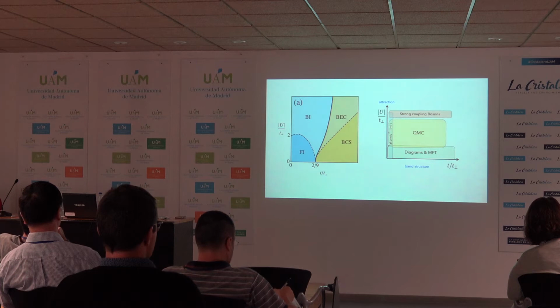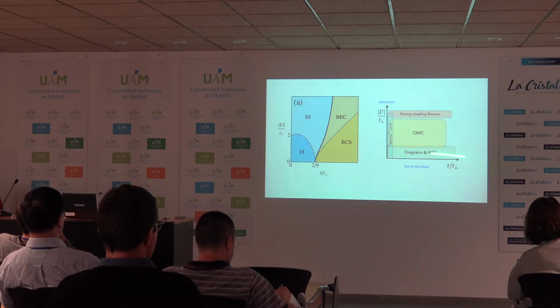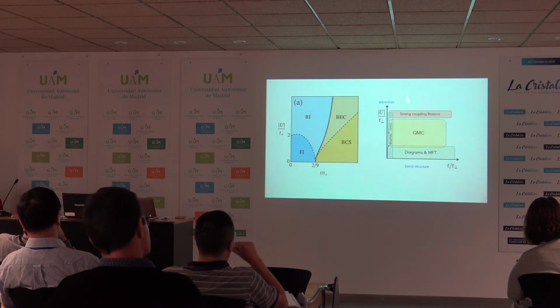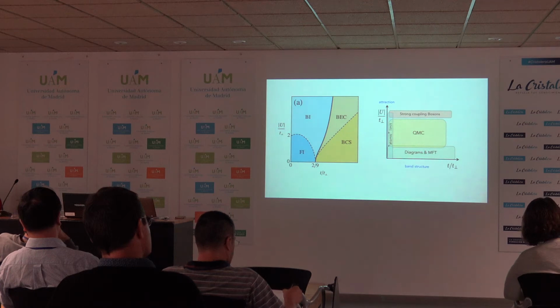Clearly you can see this is ideal for testing many different approximations. So when U is small, then we can do diagrams and mean field theory. At zero hopping, we can essentially analyze the atomic limit. At strong coupling, we can map the problem to bosons and look around that limit. And really in the middle, when all the energy scales are of order 1, then you have to use quantum Monte Carlo. And the result of that is a phase diagram like this.